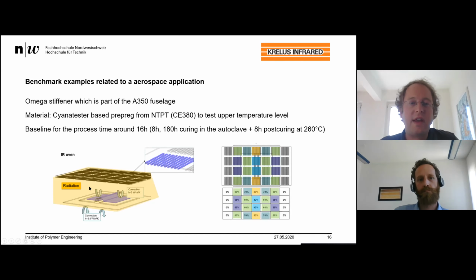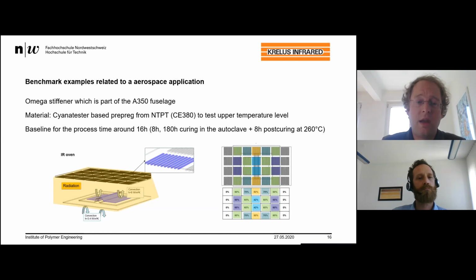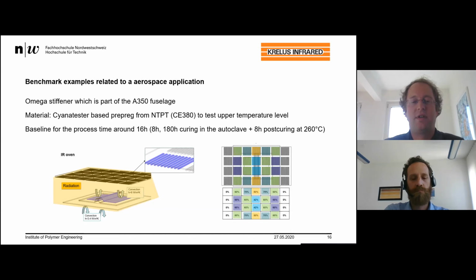So coming to the first example, this you have already seen in the video itself. There we are curing these omega stiffeners, which are related to aerospace applications. For instance, if you have the stiffening elements in the A350 Airbus airplane, there you find such omega stiffeners which are applied in the fuselage. And the material which we are using here is not a common material. It's not an epoxy-based carbon fiber prepreg. It's a cyanate ester-based prepreg.